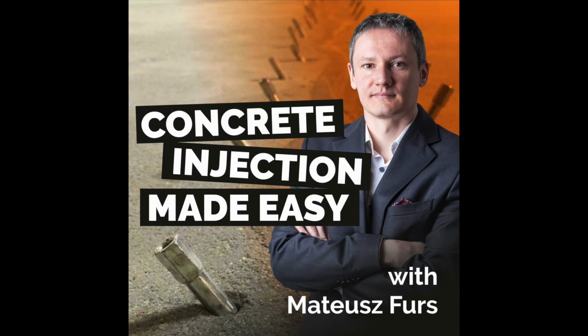Characteristics, advantages. Key difference between PU, which is also known as elastomers because they are highly elastic and retain their elasticity over time, and EP, which are duromers, forming a rigid structure when fully set. Both PU and EP form an effective barrier against water infiltration and corrosion, but only epoxy resins structurally bond the concrete sections together and so can restore the original characteristics of the structure. Again, this happens mostly in dry conditions.